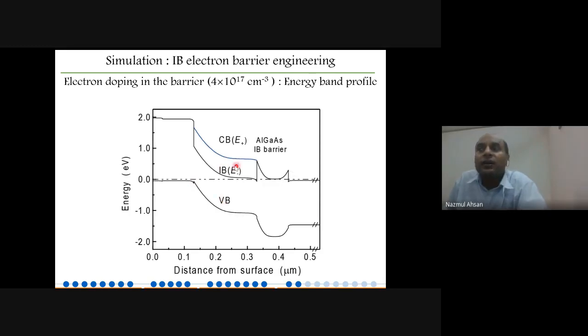This is not under sunlight. This is at dark. So we design, and on the next slide, let's say you dope your intermediate band, and you have a high band gap barrier here. If you change the doping concentration, so if your doping is high, let's say 4 times 10 to the power 17 in the barrier, then you have a very thin barrier here. Most of the electrons can pass through this by tunneling.